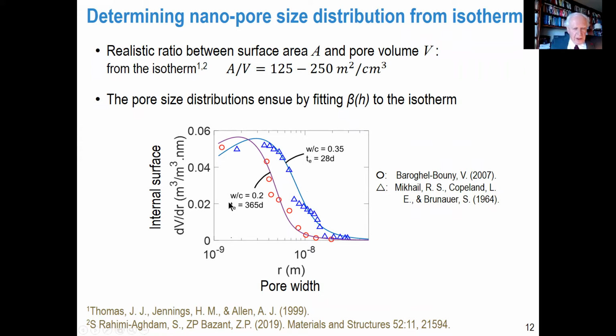We show here some of the results that we got, fitting the data of Baroghel-Bouny on internal surface versus pore width. This is the red data points, and classical data by Copeland from Portland Cement Association in Skokie next to us here, and these are the triangle points, and you see that predictions fit very well.